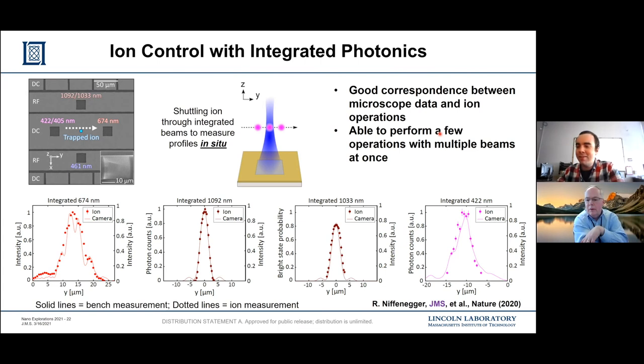For a lot of previous work that was done with this kind of packaging, you'll see a glue where they just allow the glue to go into the interface between the fiber array and the edge of the chip. But for some of the wavelengths we wanted to work with, like 420 nanometers and below, a lot of epoxies and glue undergo what's called yellowing, or they become opaque when they experience bluer or more UV light. So one challenge is an epoxy that isn't going to wick into that interface. You wanted to just keep the two together and then glue on the outside.